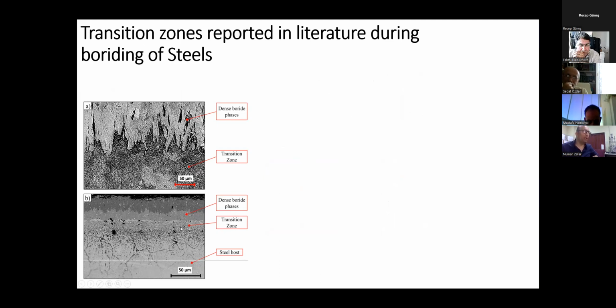A similar thing has been reported for surface boriding, but that is a completely different phenomenon. What happens there is that after the formation of the iron boride phases on the surface, there are some regions right here, known as the transition region, where the diffusion of boron to the host steel is not complete. That is why softer regions are formed. High hardness region, low hardness region, and substantially low hardness region in the host.